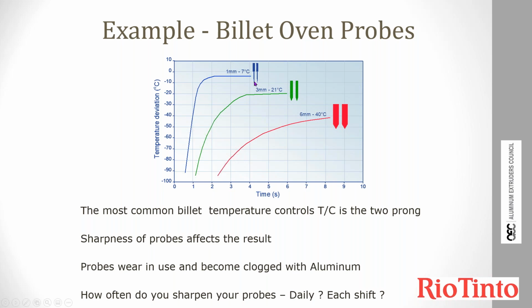But when the probes start to get blunt, they don't penetrate the oxide layer on the billet as well. You don't get such an accurate temperature reading. They build up aluminum. That encases the mass of the probe again. And we start to get under readings. Well, what happens to the control system in the oven? The oven starts turning out hotter billets and hotter billets and hotter billets.